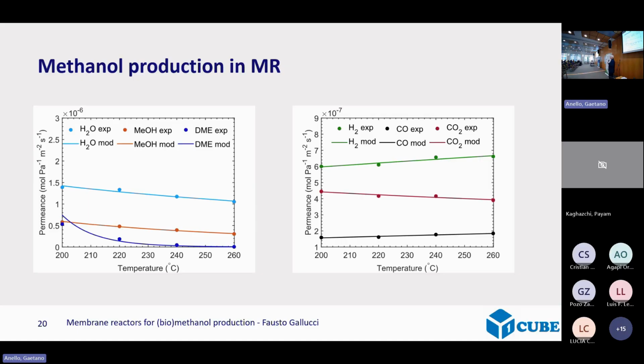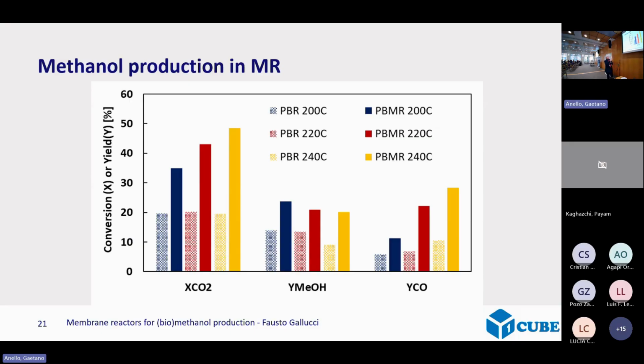So if you would have a selectivity that is 100% for water, then you get a single pass increase of conversion, and you don't need to do much more. If you have a selectivity that is lower, then what kicks in is the reactor design. You can still get better conversion. And here are the results. You see that a membrane reactor compared to a conventional one has an increase of conversion per pass quite remarkable.